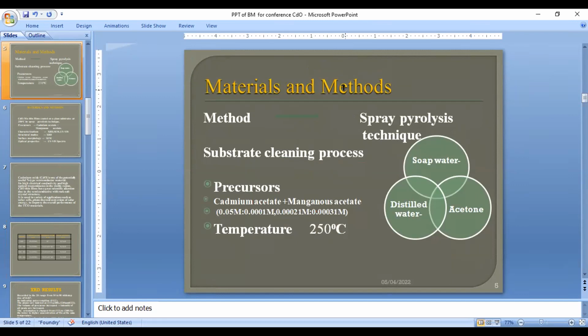So the precursors we have used are cadmium acetate and manganese acetate. For the various molarity ratios, we have taken 0.05 as constant for cadmium, and the various manganese ratios are 0.001, 0.002, and 0.003 molarity. The optimum temperature will be 250 degrees. Among the three molarity concentrations, 0.002 gave the more appropriate result compared to the other two.